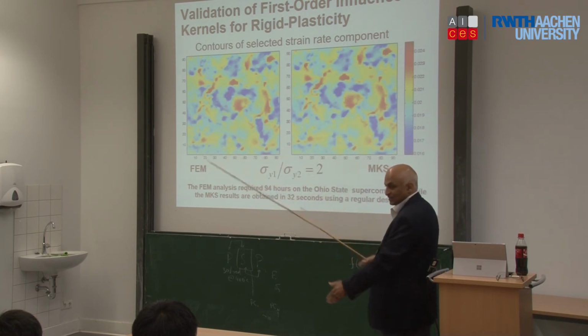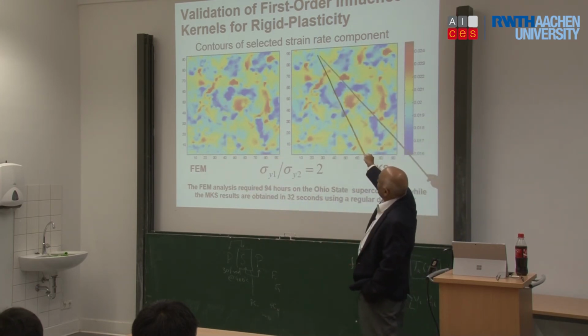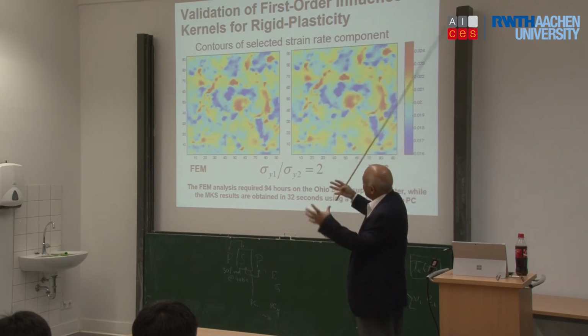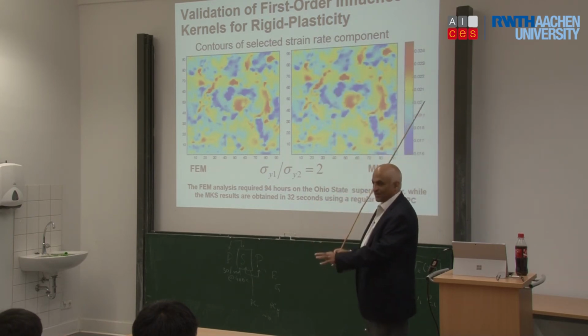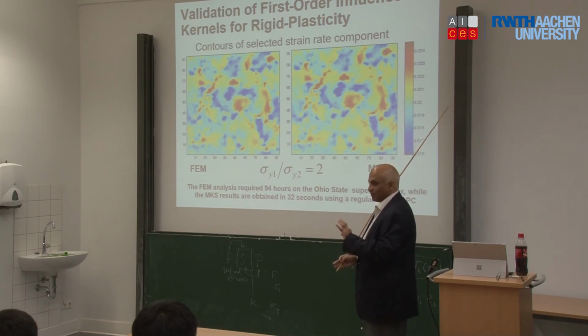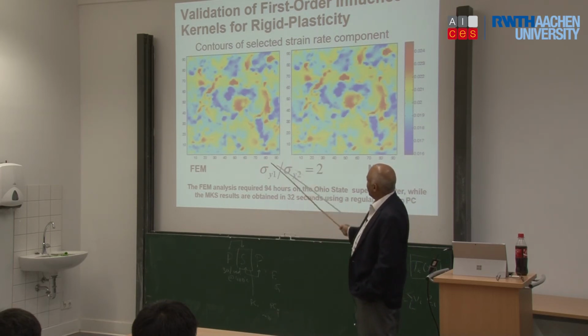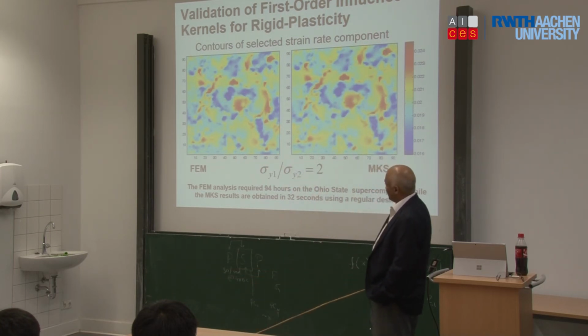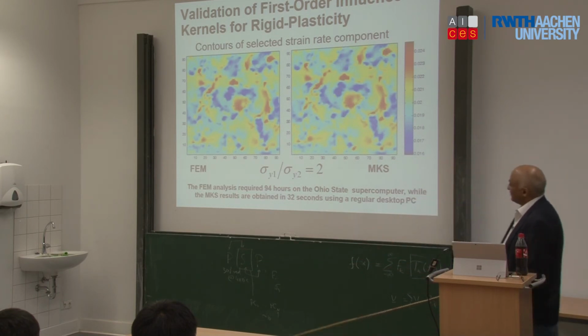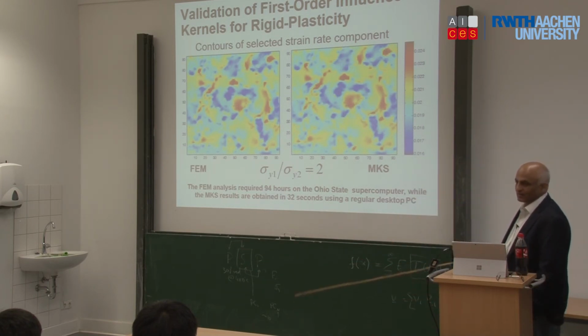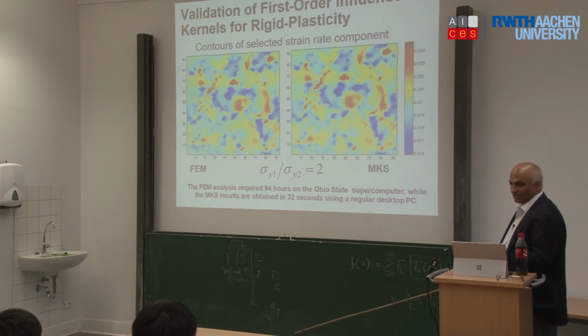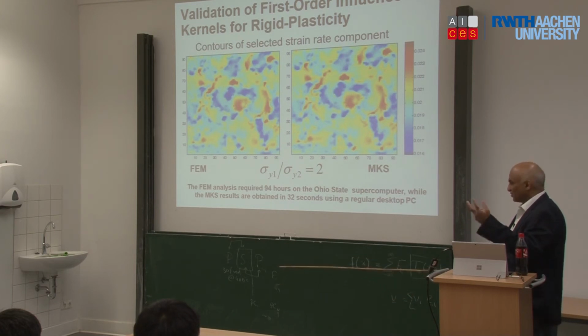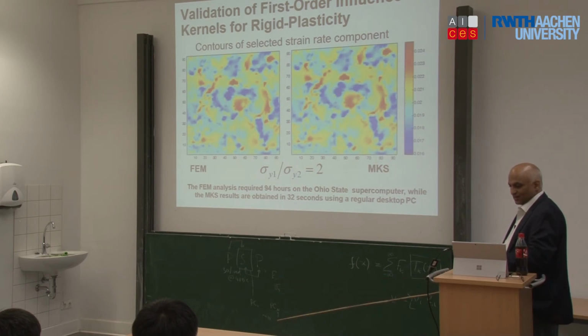I'm showing you midsections, and these are a particular strain rate. So, in plasticity, we impose a global strain rate, and we want to know the local strain rates, component by component, and this is one of the components. And of course, the MKS part is very fast, incredibly fast. You can do it with very little resources, right? Because of the DFTs. All I'm using are DFTs. I just need to do one DFT because the kernel is already in DFT. I have to do 2 because I have to do an inverse DFT. So, I have to do 2 DFTs, and then it's over.